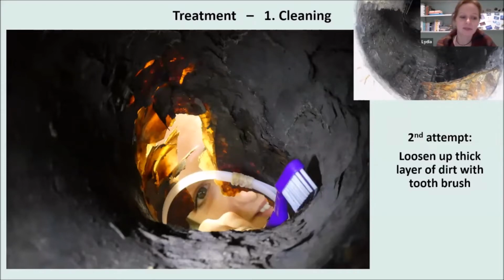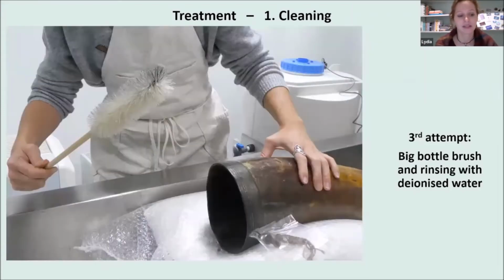While testing these cleaning methods, I noticed that the horn material is actually much more stable than initially thought, even where cracks in the lamination occurred. Additionally, the water helped to relax the laminating layers, which made them more flexible and reduced the risk of breakage. This information and awareness gave me the confidence to take a more drastic approach, even when the step still brought me out of my comfort zone, as it is not the way I would normally treat a museum object.